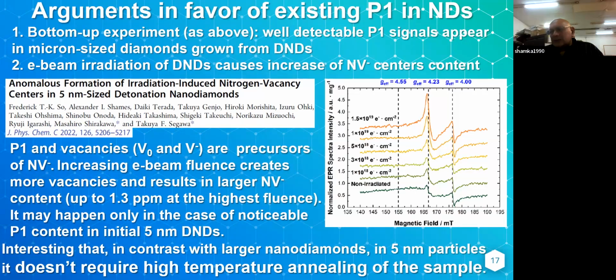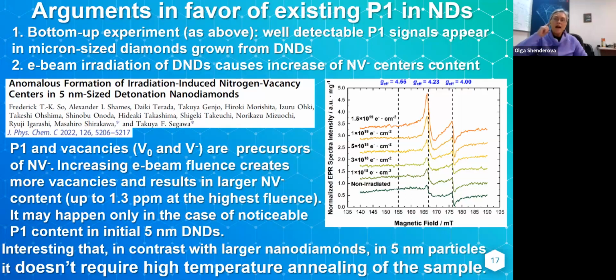It's one of the possible explanations. But what's interesting is that, except for this forbidden signal, the so-called allowed signals in small nanodiamonds disappear as well. It's still not explained, but I think that the mechanism of disappearing of these lines should also be related to exchange interactions between all the centers inside, because you have a very dense salad of different centers, and all of them interact.